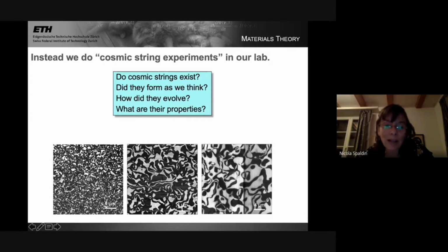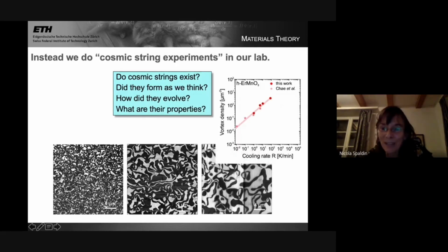The way we study that is by cooling our multiferroic at different rates through its phase transition and seeing if we get more or fewer of these intersections between the ferroelectric domains. I haven't cheated here. The scale in all cases is the same. It's a 4 micron scale bar. So one can have an undergraduate intern count the number of intersections in all of these cases and see how they vary as a function of cooling rate. And we do indeed see, if we plot the density of these intersections as a function of cooling rate, the red line is the prediction for cosmic string formation, and the red dots are the data.